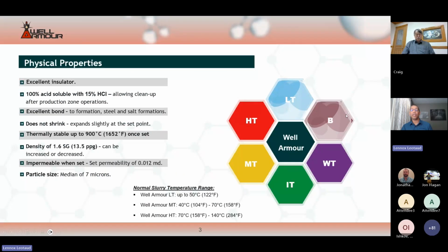The Well Armour slurry, depending on application temperature and set time needed, can, in a majority of cases, be a 2-component system or even a 3 or 4-component system of slurry. Shown here are all the basic components used to formulate a Well Armour slurry. All of the component materials are solid except for the Well Armour WT, which is a liquid. The makeup of a typical low temperature application Well Armour slurry is usually the Well Armour LT powder plus the Well Armour B added to water.